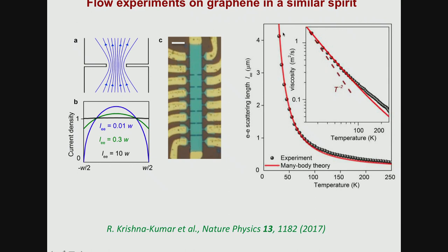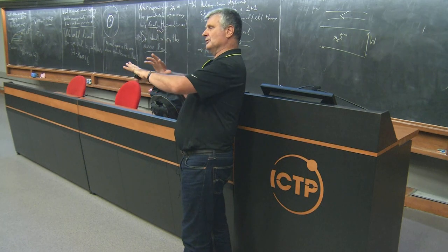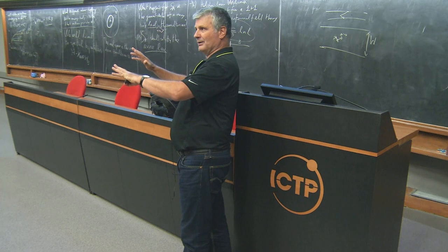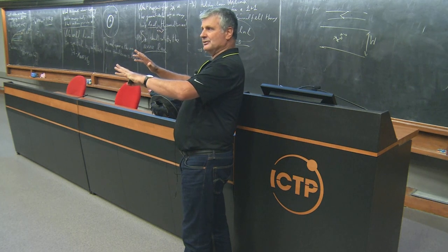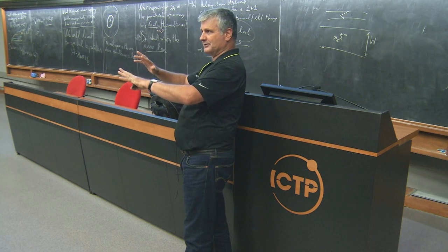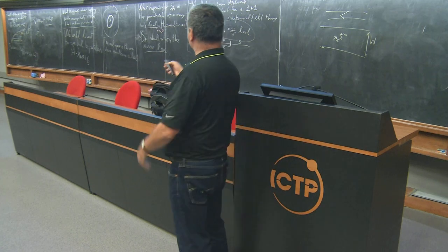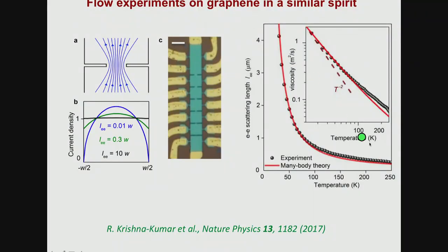Now, we can't do that because we're saying that phonon drag is the source of our collisions. The phonon drag length is extremely difficult to calculate as a function of temperature because you're making a crossover from normal to umklapp events. You don't have a circular Fermi surface. So we can get something which looks temperature dependent, not so far off these kinds of temperature dependencies, but we don't have an easy theory to compare it to.